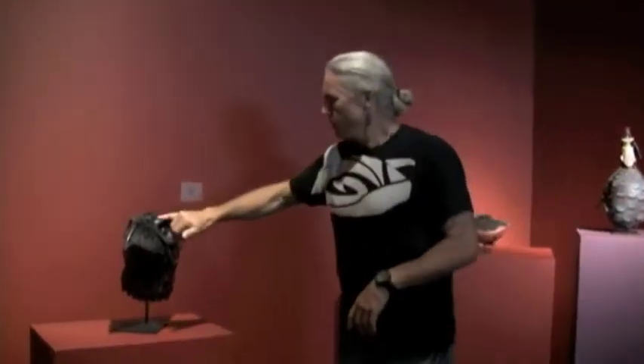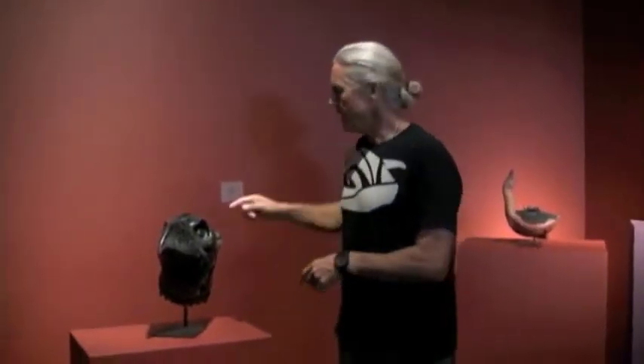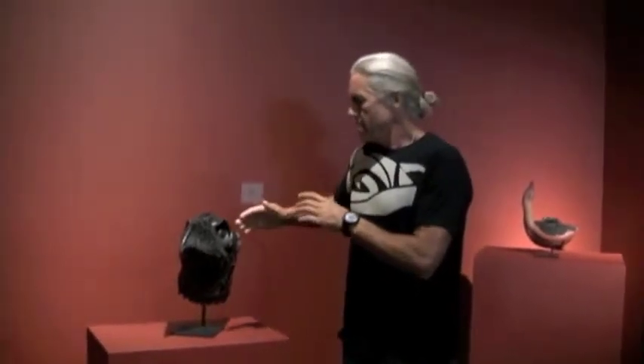And is that piece sandblasted? There's no sandblasting. The way these pieces are done is that we make what we call a blank, which is a small vessel that has a very small opening, and it is cooled in the annealer, and it has layers of color on it. Well, when we cool that, the gentleman who did the carving on this is here. You'll notice by his size, he's the largest guy in the museum. Rick Allen. Rick and I worked together for decades, and he would carve out the color, and then we would put the vessel back in the oven, heat it up, and pick it back up under the blowpipe, then blow it and shape it. So the design would follow the form that you would continue to shape. So that's why it gave it that feeling of belonging more to the shape than just being applied. That's one of the great qualities about the material.